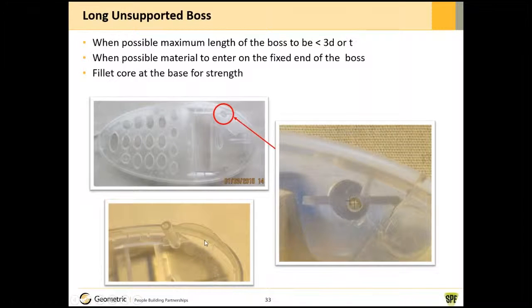This hole is created by a slender pin that's going through this length, and that's subject to up to 20,000 psi of plastic pressure. It's acting like a cantilever with 20,000 psi acting on its tip, and it's going to bend, and ultimately it's going to bend back and forth, and ultimately it's going to crack due to fatigue. But in the process of bending, it's causing the hole in the boss to be not concentric with the outside.